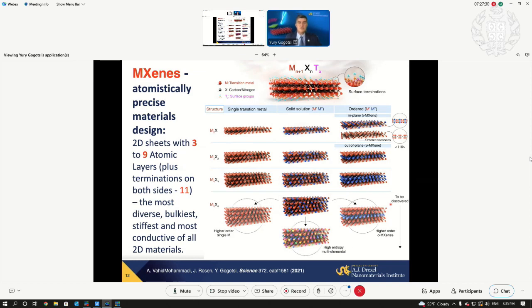Moreover, as I already mentioned at the beginning, we have a variety. We really design atomistically precise materials with different numbers of atomic layers. We can make atomic sandwiches where one transition metal, for example, chromium or moly, is on the surface. Another element, for example, titanium, is in the middle. Or MXenes ordered in plane, with alternating atomic columns, probably easier to see in a 2D projection, with alternating elements. And if you remove one, you get rows of vacancies, divacancies on the surface. And of course, I mentioned, we can mix and match, make solid solution. If we take 4 or 5 transition metals, we can make high entropy, multi-elemental MXenes. So the sky is the limit.